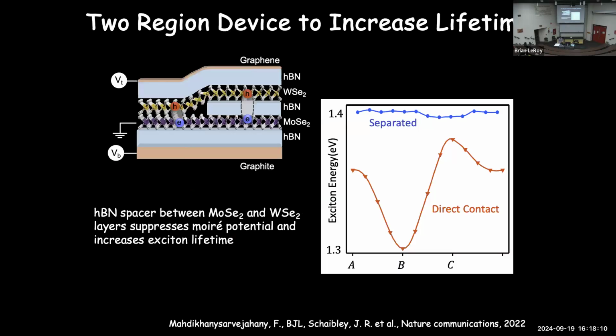If you want to make them live even longer, you bring these materials apart, making it harder and harder for those excitons to recombine. So in this case, I have the materials in contact. The electrons and holes are here. As I bring them apart using a boron nitride spacer, I separate the electrons and holes, I make it more difficult for them to recombine, and I then increase the lifetime of this state.